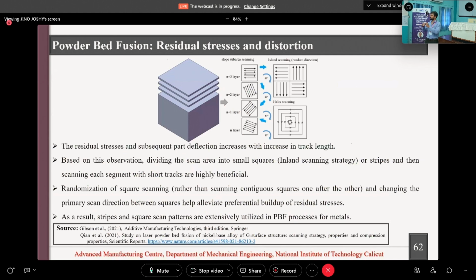As I have already explained, in order to reduce the residual stress impact or randomly distribute the residual stresses, we are using different scan strategies. Here you can see that the residual stresses and the subsequent part deflection increase with increases in the track length. So in order to avoid that, we use a very small track length, that means in infill mode, and we also change it in the different layers.